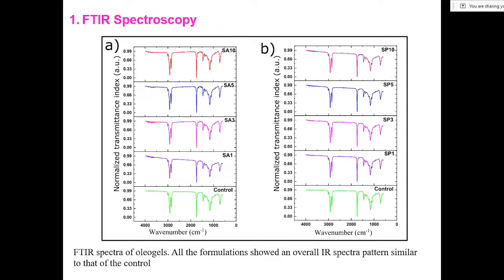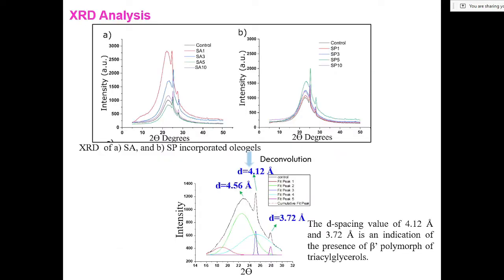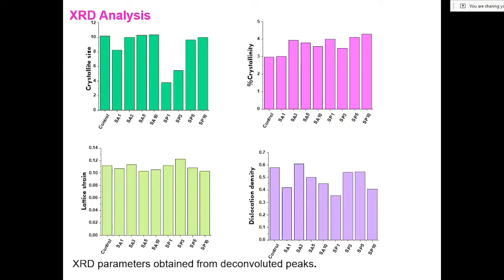So these are just the FTIR spectroscopic results, and I will not go into the details. For confirmation, we went for the XRD analysis. In all the samples, we found peaks at d equal to 4.12 angstrom and d equal to 3.72 angstrom. The presence of these two peaks confirmed the presence of beta prime polymorphs of the triacylglycerols in the oleogel system. From there we calculated the crystallite size, percent crystallinity, lattice strain, and dislocation density. If you see, the crystallite size varies as we add the emulsifiers in different concentrations. Similarly, the percent crystallinity varies, lattice strain also varies, and finally the dislocation density also varies.